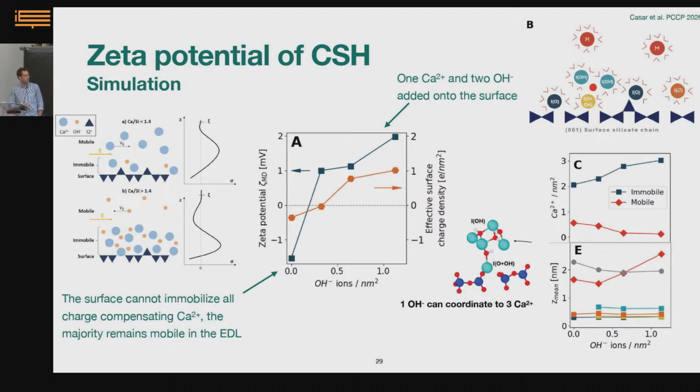Then your anions, OH minus or chlorides or whatever, move closer to the surface and become the dominant ion that moves the water, but it moves it in the other direction, so it gives you positive zeta potentials. So that's how we figured out that OH minuses are key for surface complexation.